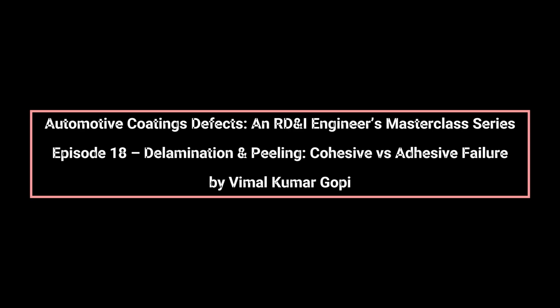Silicone residues, surfactant migration, oil mist, or even excessive flow additive accumulation can lower surface energy enough to cause adhesion loss without visible defects. Cohesive failure, on the other hand, indicates that bonding was stronger than the internal strength of the coating film. This is often caused by over-cross-linking, excessive brittleness, or internal stress buildup.